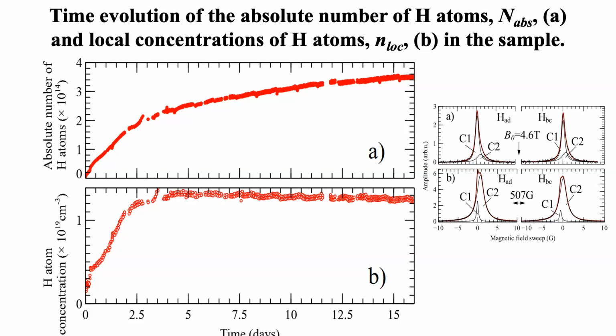Seeing this curve, we developed a model. We suggested that at the first stage, we create a high concentration layer of hydrogen, and after that the concentration doesn't change. But because the total number is increasing, it means that this high concentrated layer moves inside the bulk H2 film, and we can follow the speed of propagation of this high concentrated layer.